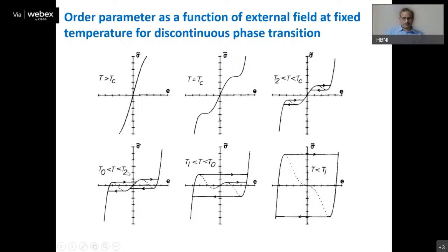Now, if your temperature is further lower than some spinodal temperature, in this case, even if you completely remove the external field, your phase will not transform back to the initial phase. So you have to apply field in the opposite direction. If you have, suppose, a one directional order parameter, which means the free energy is not symmetric, in that case this will correspond to an irreversible phase transition. And if your temperature is further lower, then there is very little scope for this initial phase to exist. So the only stable phases are the two transformed phases corresponding to the two different non-zero order parameter values.